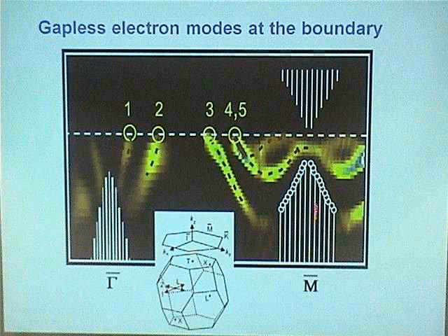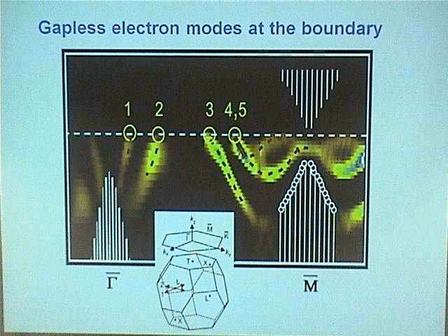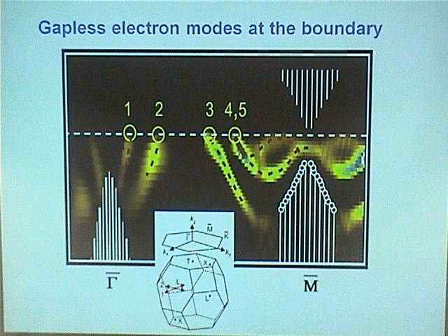I haven't proved that this is holding, but at least I know that at the Kramers point, the states are degenerate, and there is a Dirac point there. It's degenerate with the bulk. That's why imaging both at the same time is difficult for us, but you can see that if you extrapolate, this is another Kramers point. So at least despite disorder and other things, the Kramers point is not broken. That's very exciting, that the Kramers point is intact.